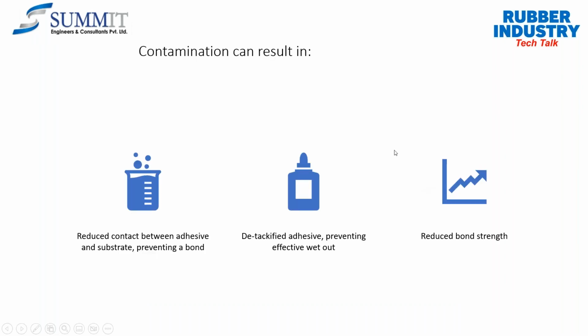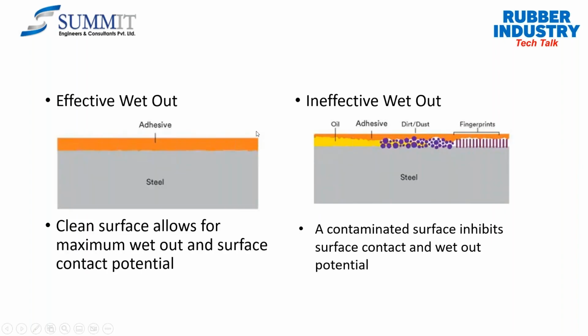And this particular contamination, if by chance it is present, can result in reduced contact between the adhesive and the substrate, preventing the bond. Okay, or the proper bond will not happen. The contaminated adhesive prevents the effective wet out and reduces bond strength. So all such things can be avoided by utilizing the effective wet out. Let me explain it with the help of this figure. The clean surface allows for the maximum wet out and the surface contact potential,